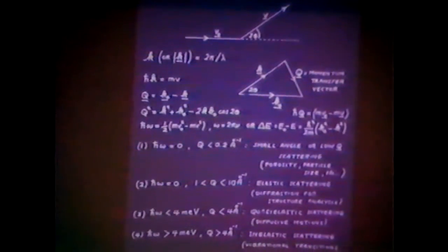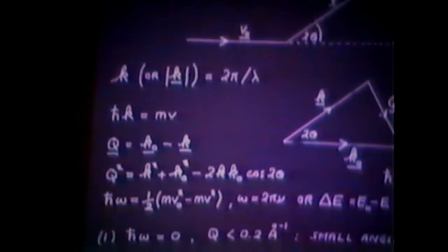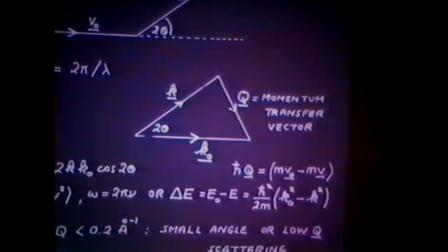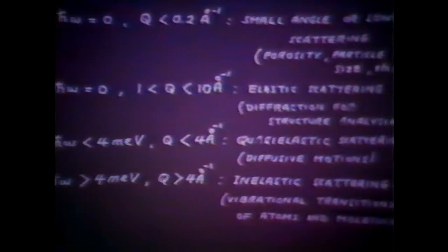What's next? Now that brings me directly onto neutron scattering. The comparison with infrared: well, you all know about infrared and pressed discs and diffuse reflectance and so forth. The one big disadvantage with infrared is basically you've got to press a disc that will stay together. And it means a thin disc, so you've got to have a high specific surface area. Also, there are selection rules. Now, the neutron method has the advantage that you can use quite large samples. You don't have to press discs. Also, there are no selection rules.